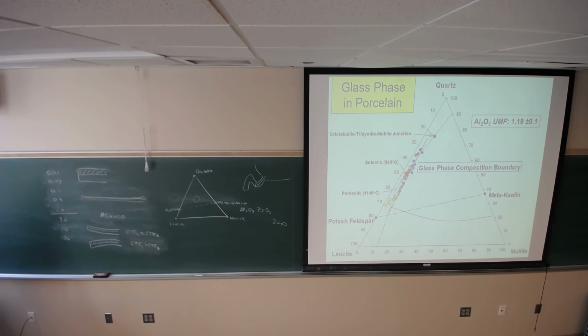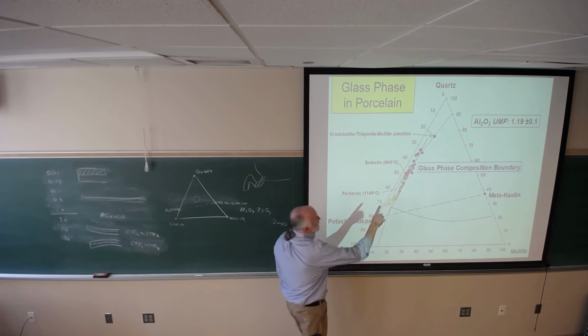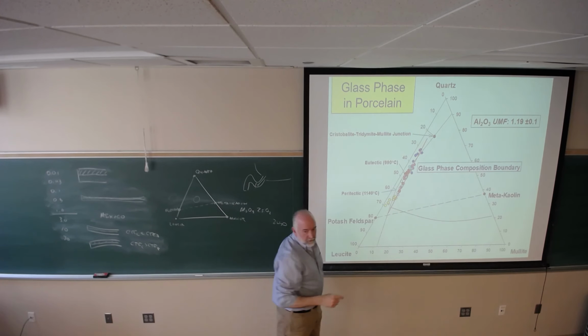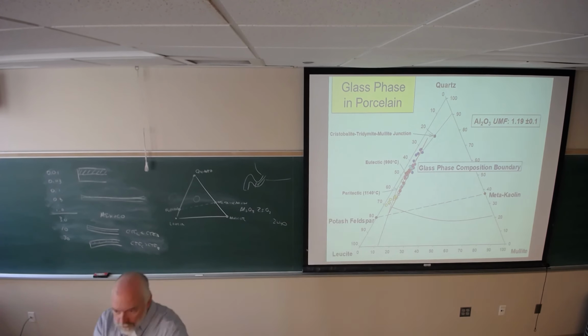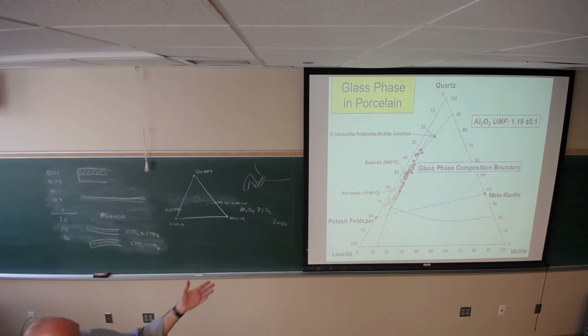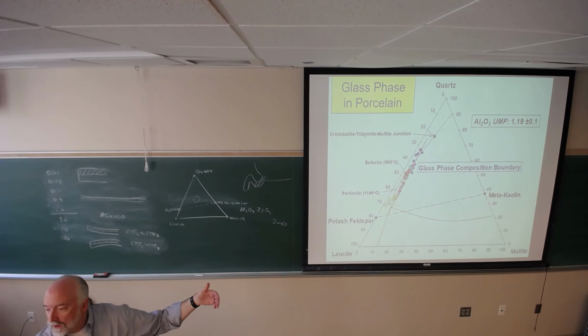So what we did several years ago is that we measured the chemistry of the glass phase for 100 different samples. And since that time, many more. And what we find is that the chemistry of the glass phase is remarkably uniform. And it falls in this line. Okay? And this line is roughly 1.2 moles of alumina per mole of flux. We're back to our UMF view of chemistry of glass. 1.2 moles of alumina per mole of flux. It doesn't fluctuate. It's 1.2 moles of alumina plus or minus 0.1, which is a really narrow margin, okay, per